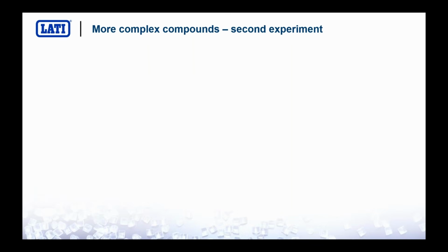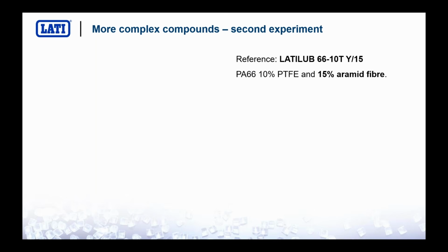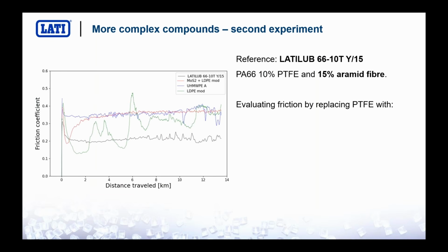We made also another experiment, so we tried to replace PTFE in a material that I have already mentioned, the polyamide 66 with 10% of PTFE and 15% of aramid fibers. And we tried different additives in order to replace the 10% of PTFE. The black curve is the reference, so the behavior of PTFE plus aramid fiber.